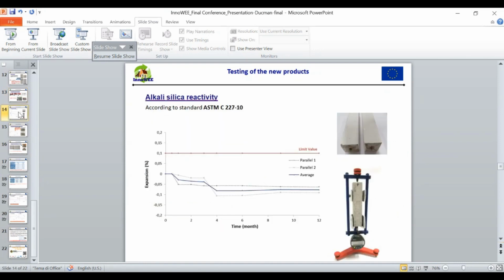The next parameter is alkali silica reactivity. This is also very important because such a reaction might take place under certain circumstances and cause expansion, and if it causes expansion, the material is deteriorated. So we also tested our geopolymer panels regarding alkali silica reactivity. Samples were exposed to high humidity and an elevated temperature of 38 degrees C for a whole year. It was confirmed that there is practically no expansion. In fact, samples shrank a bit and stayed stable over 12 months. For cement-based material, the limit is 0.1%, but the alkali silica reactivity of our samples is far below these values.